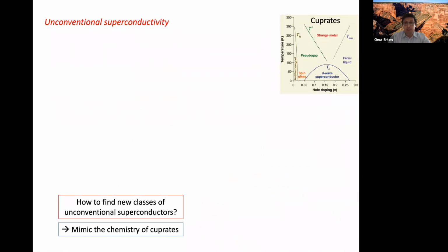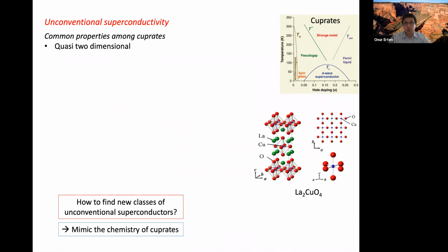Okay, so what are the minimal things we want to distill from cuprates, such that if we want to make similar compounds, what do we need to include? So the cuprates have this crystal structure called Ruddlesden-Popper or layered perovskite structure, where the coppers are in an octahedral coordination of oxygens, and in the two-dimensional plane, they form a copper oxide plane. And these copper oxide planes are layered in between rock-salt slabs, meaning that it's not really two-dimensional or three-dimensional, it's quasi-two-dimensional. So we want quasi-two-dimensionality.